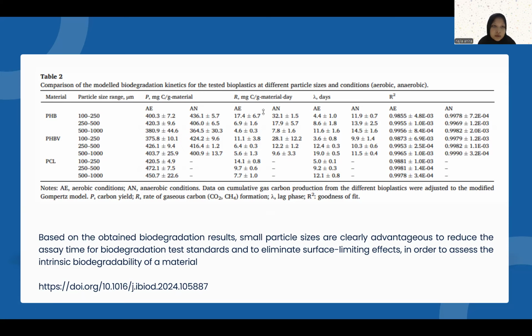In this table, the materials used are PHB, PHBV, and PCL, where this is the particle size range in micrometers, and this is the days for the lag phase, and R is the rate of gaseous carbon dioxide and methane formation, and R square is the goodness of fit. Based on the obtained biodegradation results, small particle sizes are clearly advantageous to reduce the test time for biodegradation to standard and to eliminate surface limiting effects in order to assess the intrinsic biodegradability of a material.